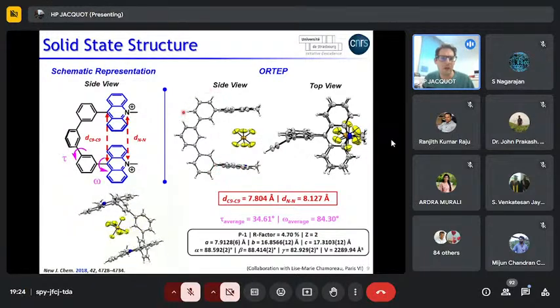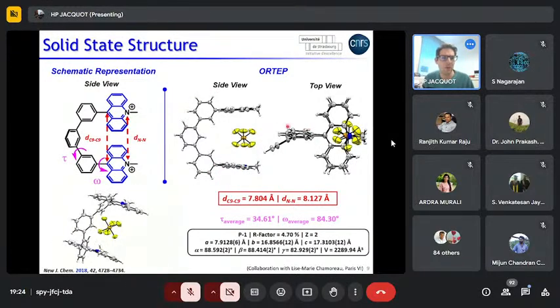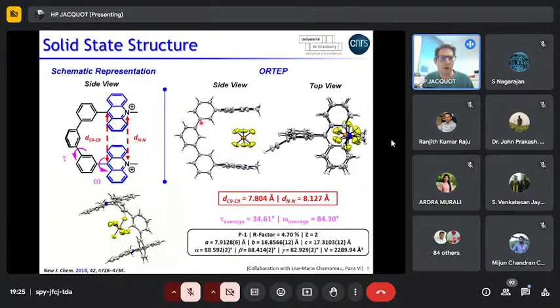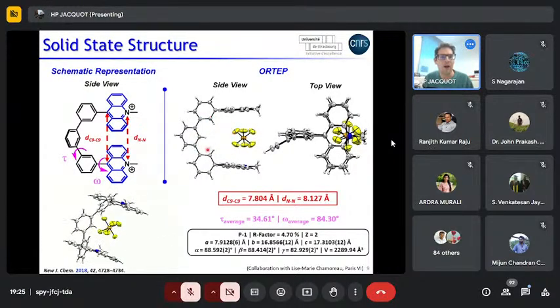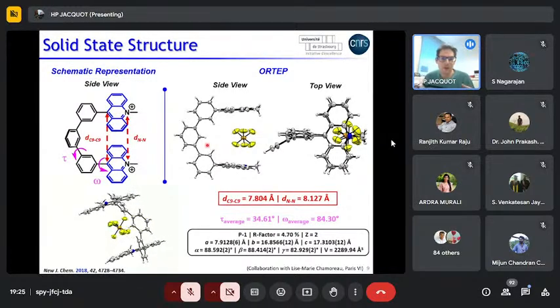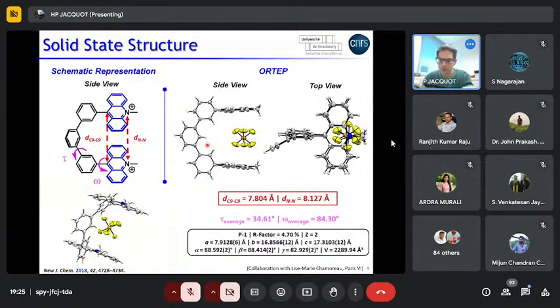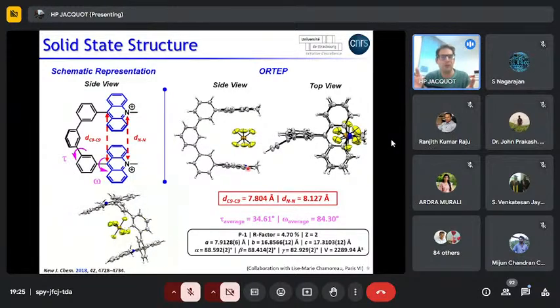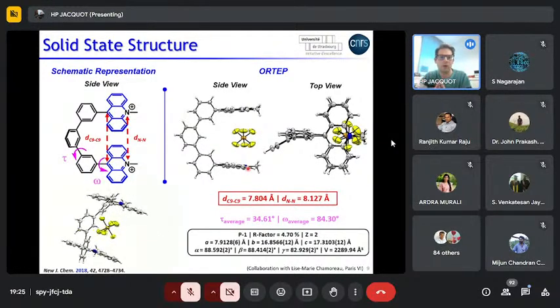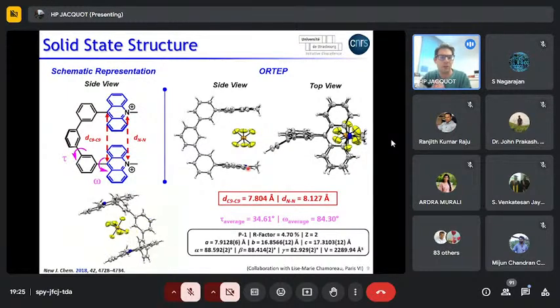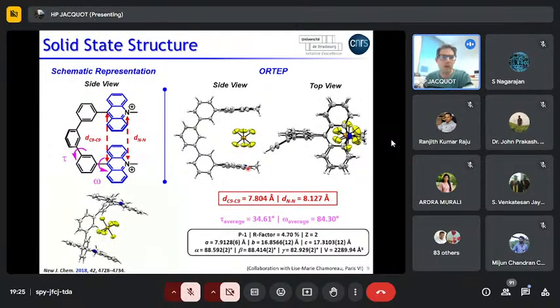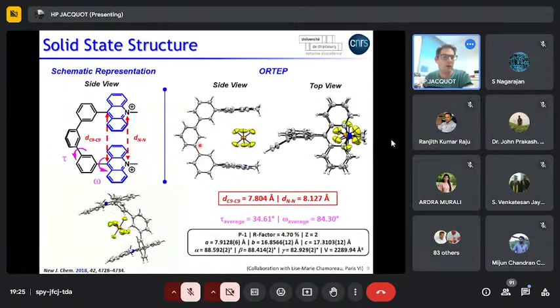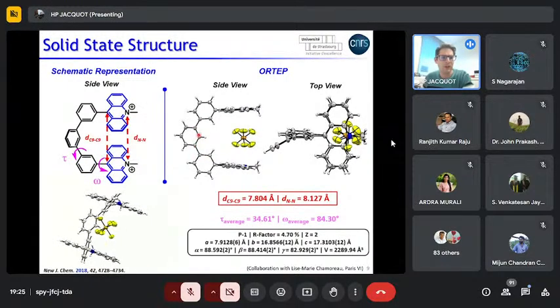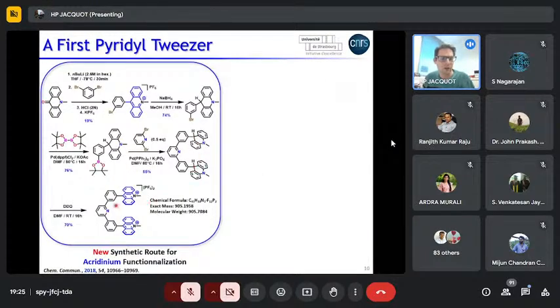If you look carefully at the spacer, it's distorted because there is a steric clash. You have 3 CH bonds pointing in the bay area of the spacer. So this steric clash moves apart the two acridiniums, and like this, you reach a distance of 8 angstroms. This means that if you want to have the two acridiniums close to the optimum distance for pi-pi stacking interactions, namely 7 angstrom, what you have to do is get rid of the steric interference in the bay region. So what we've done is change this central CH into a nitrogen. And here we have the new design of the second generation of the molecular tweezers we designed.